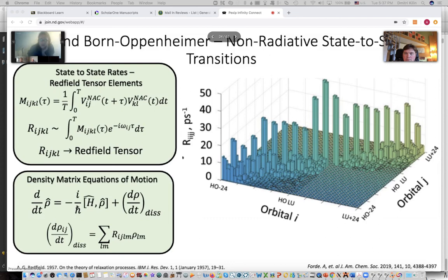So now we have our rates of transitions. And then to describe the dynamics, we use density matrix equations of motion, which is this d rho dt term here. So it follows energy conserving transitions, which is this H comma rho term. And then there are dissipative transitions, which come from our Redfield tensor. So essentially what we have is a first order differential equation with time independent coefficients. And so essentially we just code up differential equations, and then based on initial conditions, we let the dynamics run. And that leads into the next slide.